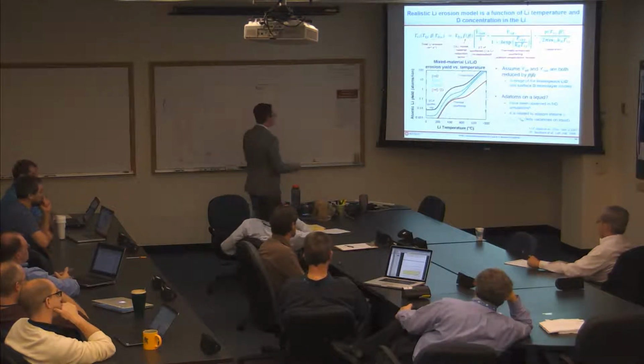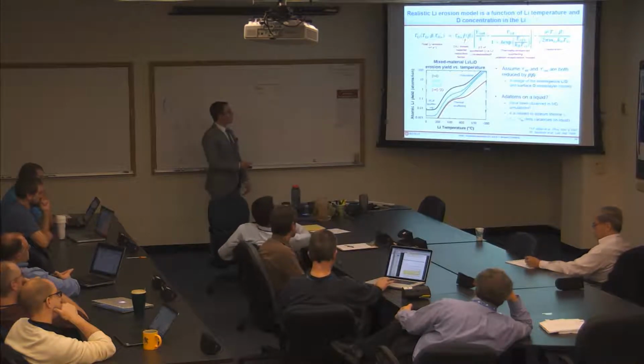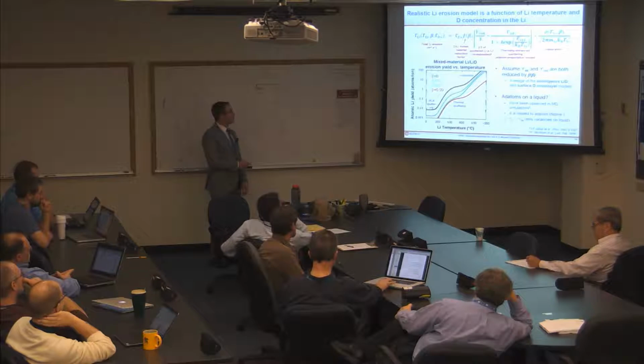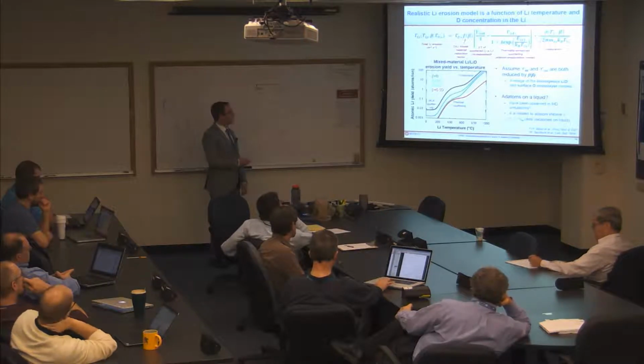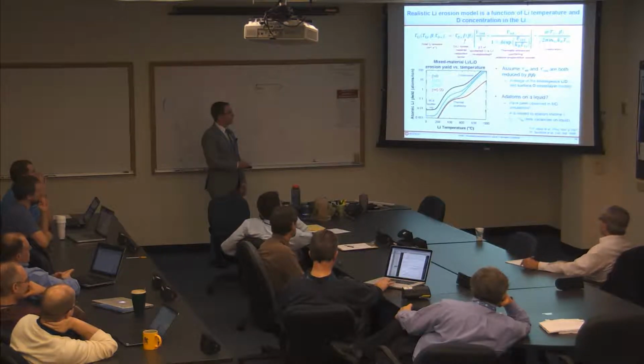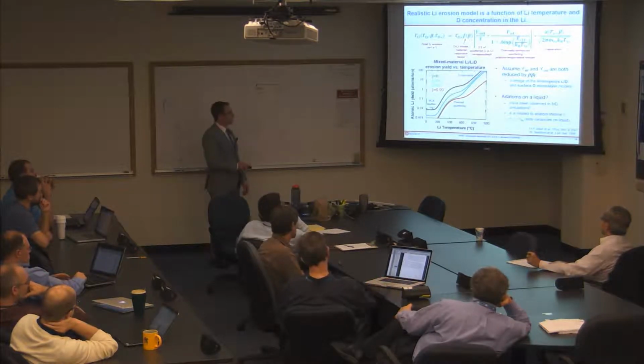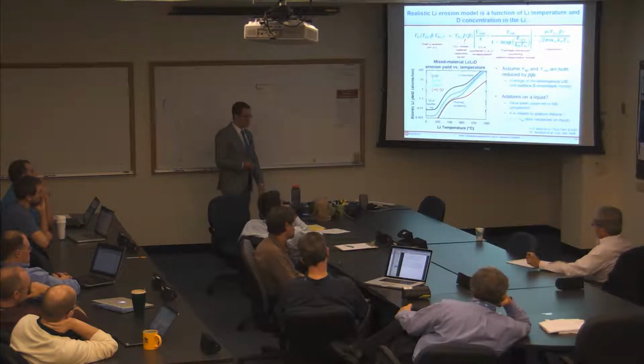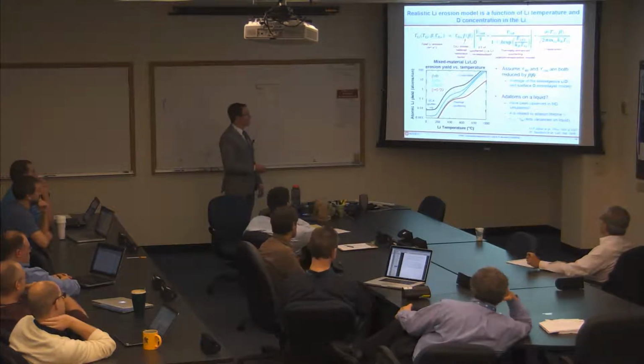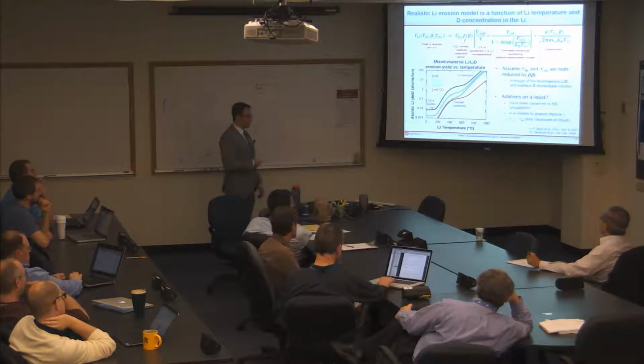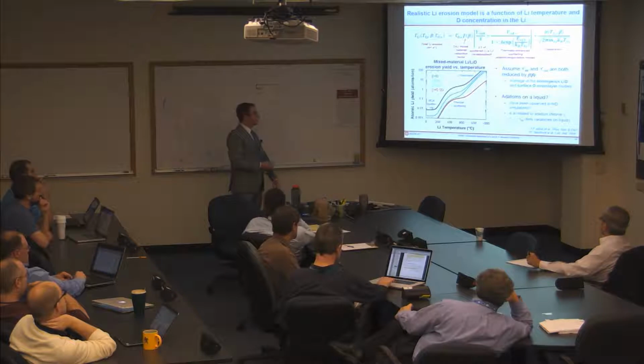Okay, so now we can put everything together, and we have the flux of lithium from a surface. This is the total lithium erosion rate, and that's equal to the ion flux times F of beta, which is this deuterium to lithium mixed material reduction factor due to sputtering that I showed you a couple slides ago. Then this term is the collisional sputtering yield for room temperature solid lithium. It's reduced by a factor of 3 because experiments by J.P. Lane have shown that 2/3 of this lithium is sputtered as an ion, and so it's assumed to be immediately redeposited on the surface. It can't escape from the near surface sheath potential.